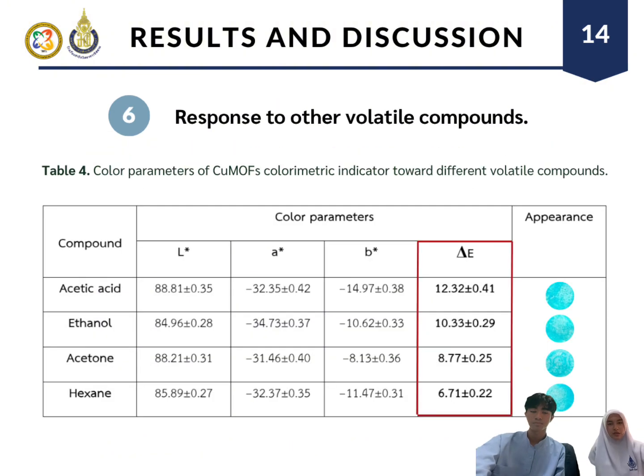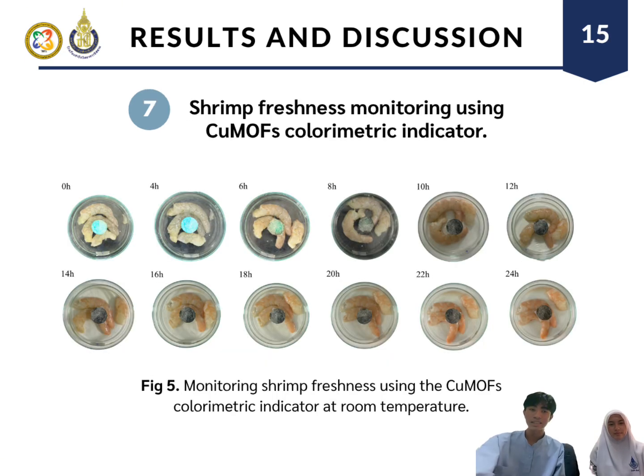During seafood spoilage, different volatile compounds such as alcohol, ketone, and acid are produced, so selectivity is important for accurate monitoring. The copper MOF indicator shows a small delta E value with these compounds, confirming the good selectivity toward ammonia. To confirm its ability for real-time intelligent packaging, 30 grams of fresh shrimp was placed in a petri dish with a copper MOF colorimetric indicator on the lid.